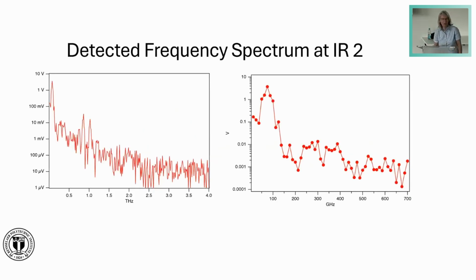Then we also did the Fourier transformation of this transient. This is the spectrum. You see that we have the noise floor, and we see that the maximum of the signal is here. And what we see is also that it rather quickly decays. This is a zoom from 0 to 700 gigahertz of this part of the spectrum. We can see that the maximum is at 100 gigahertz. But then within the next 100 gigahertz, the signal almost decays to the noise floor. So there's really a different characteristic.